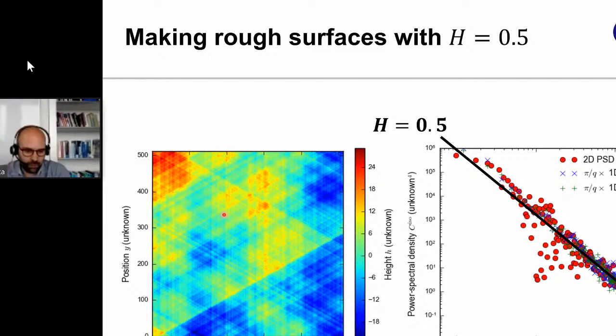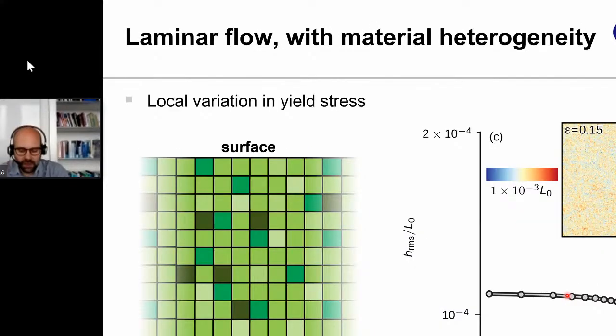We can also look at this in terms of the Fourier transform, looking at the Fourier transform of a step function. This is 1 over q, and this also leads to this H = 0.5 result. So it's sort of trivial if you think about this for metals, in which dislocations move uncorrelated. You can reconcile it with a laminar idea of material deformation, and then when the dislocations become correlated, this gives rise to different values of the Hurst exponent.